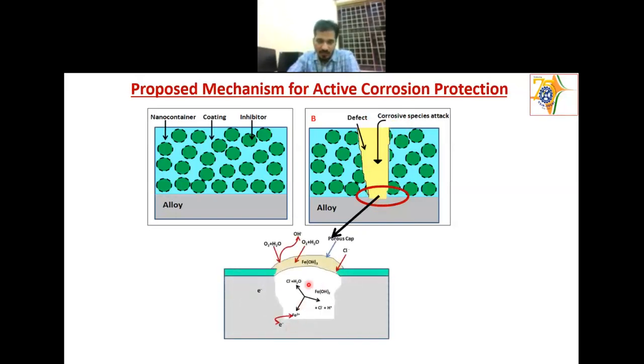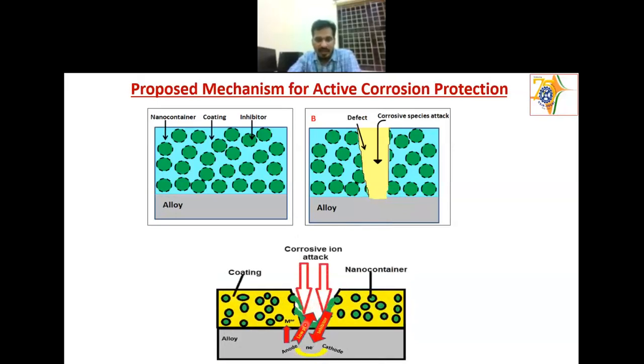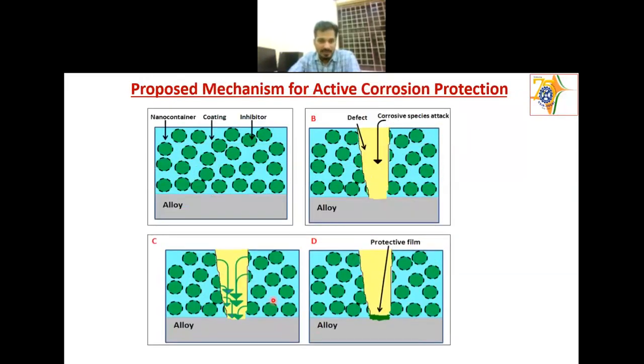At this area, when the corrosive species come, you can see the corrosion happening here, and at the defect mouth a kind of porous corrosion products will be there. Through that, chlorine and oxygen can still go inside, and these electrochemical reactions happen here. Electrons are released and consumed here. When the corrosion is happening, at the anode you can see low pH. By sensing the low pH, the nanocontainer releases the inhibitor, which can come out and stop the corrosion. The inhibitor comes down from here and a protective film is formed. So this is the mechanism of active corrosion protection for nanocontainer based coating.